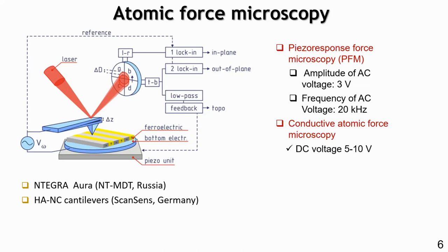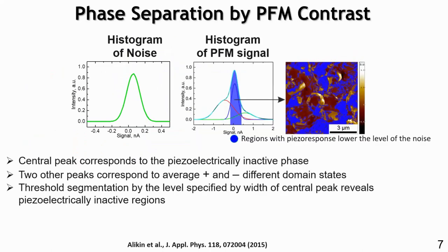With the other technique, we can also apply DC voltage to the cantilever, and in that case we will have some current flow through the tip-surface contact. And if we have a difference of conductivity in different areas across the surface, we can visualize the distribution of the conductivity by this technique. It is also important, as was demonstrated in our early paper, that we can do a quantitative estimation of how much phase is really ferroelectric in the material.